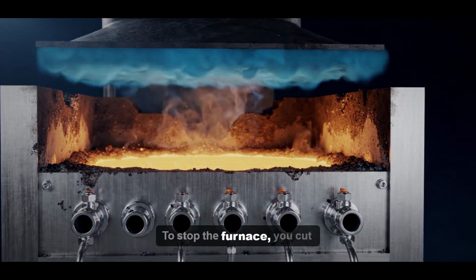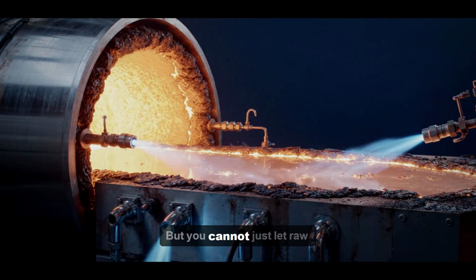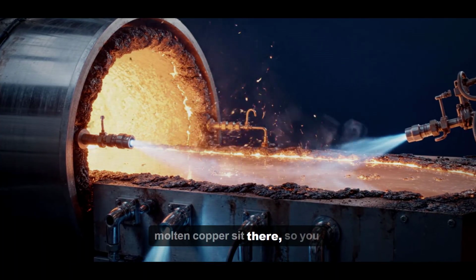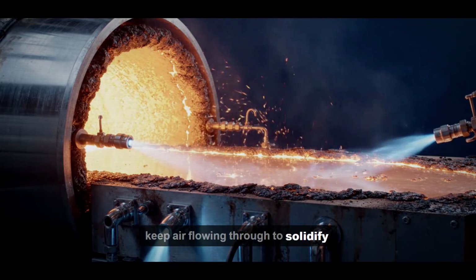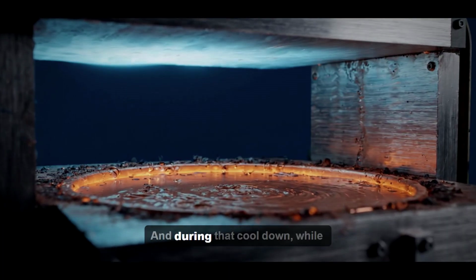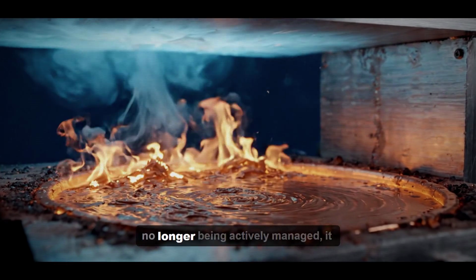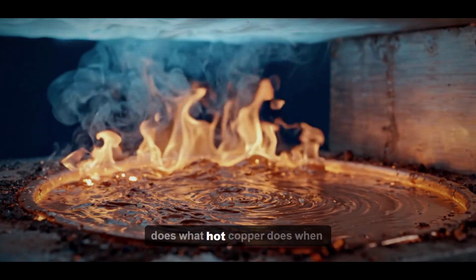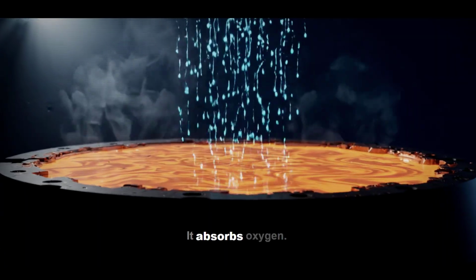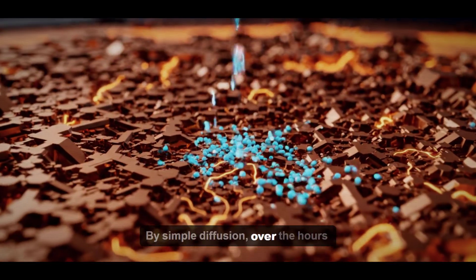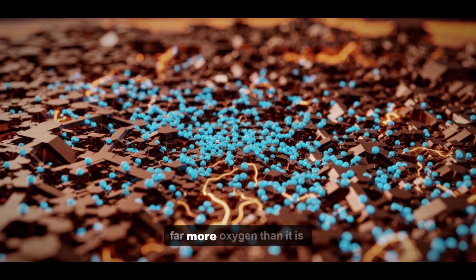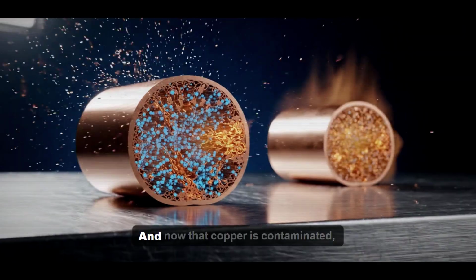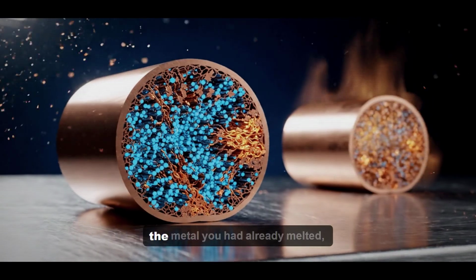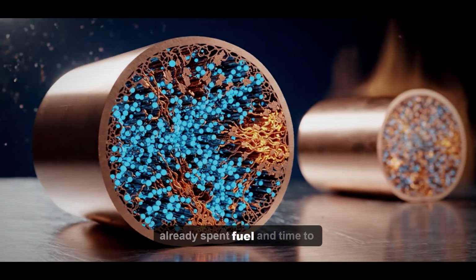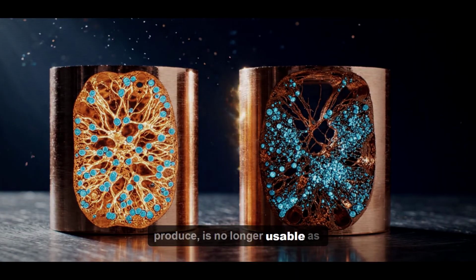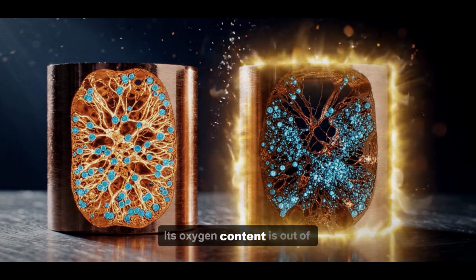To stop the furnace, you cut the fuel to the burners. But you cannot just let raw molten copper sit there, so you keep air flowing through to solidify the copper safely as it cools. And during that cooldown, while the copper is still hot but no longer being actively managed, it does what hot copper does when air is around it. It absorbs oxygen. By simple diffusion, over the hours of cooling, the metal drinks in far more oxygen than it is ever supposed to contain. And now that copper is contaminated, the metal you had already melted, already spent fuel and time to produce, is no longer usable as it is. Its oxygen content is out of spec.